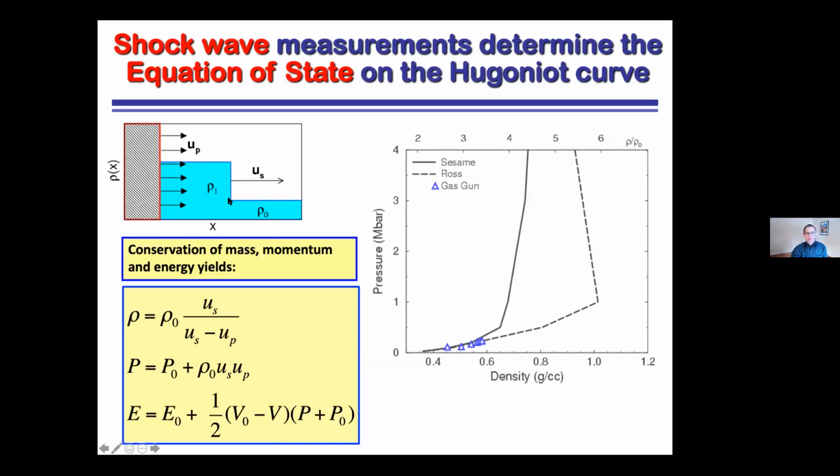And then our experimental colleagues, they measure this shock wave velocity, and they measure how fast the material has been pushed. So by measuring these two quantities, they can infer density and pressure from these conditions, and that's typically plotted here. So theoretically, what we do, we typically prescribe the volume of the simulation and the temperature, derive pressure and energy. And we solve the third equation among the Hugoniot equations, and then we predict these curves theoretically.